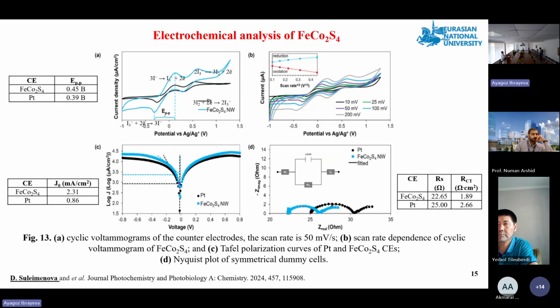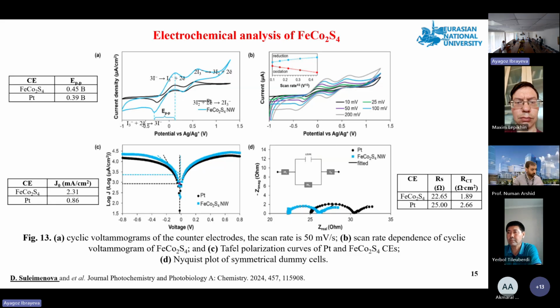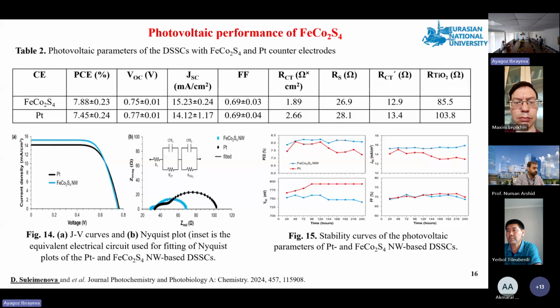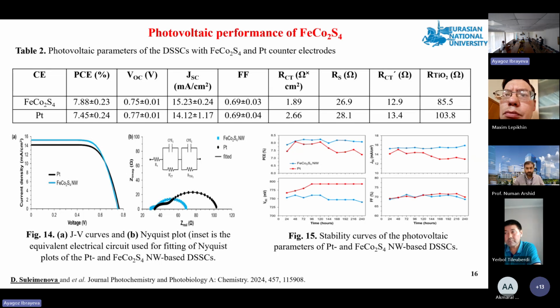Tafel analysis shows that ferrum cobalt 2 S4 has a higher exchange current density than platinum, meaning more efficient charge transfer. EIS results using symmetrical dummy cells also show lower charge transfer resistance for ferrum cobalt 2 S4, confirming fast electron transfer at the counter-electrode electrolyte interface. The cells achieved an efficiency of 7.88%, slightly higher than that of the platinum-based device, 7.45%, mainly due to a higher JSC, even though VOC and FF are slightly lower.